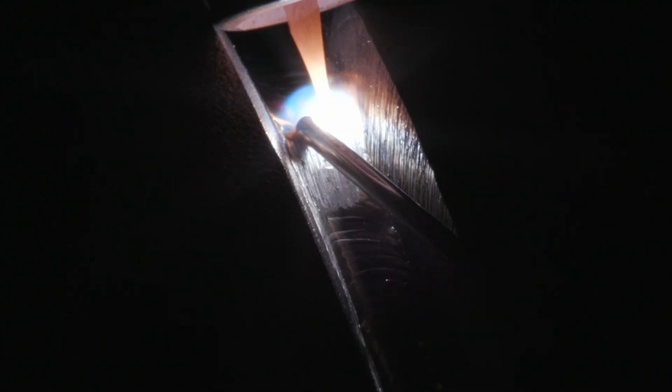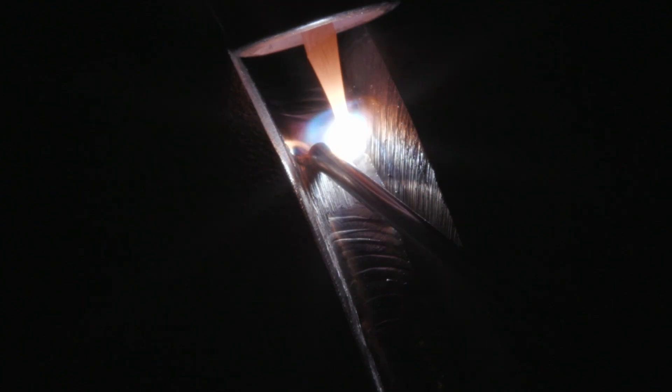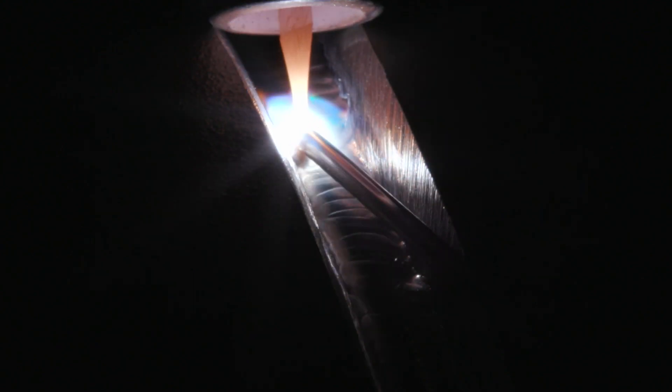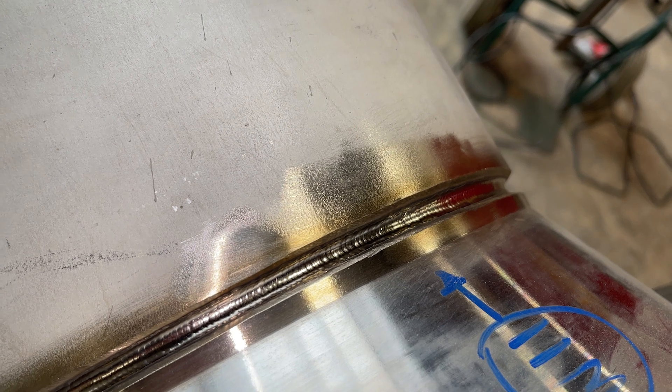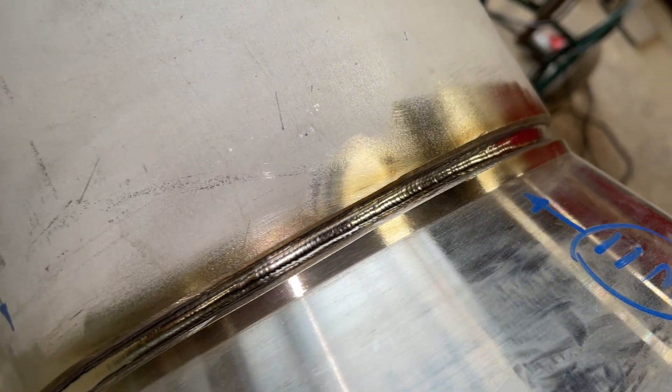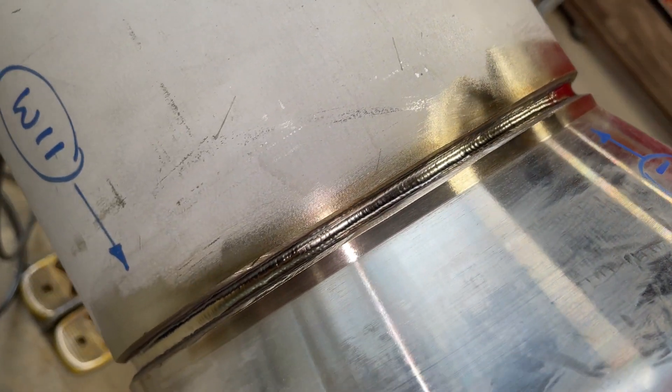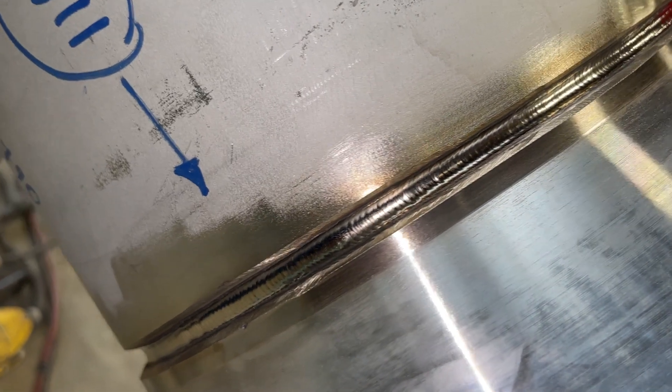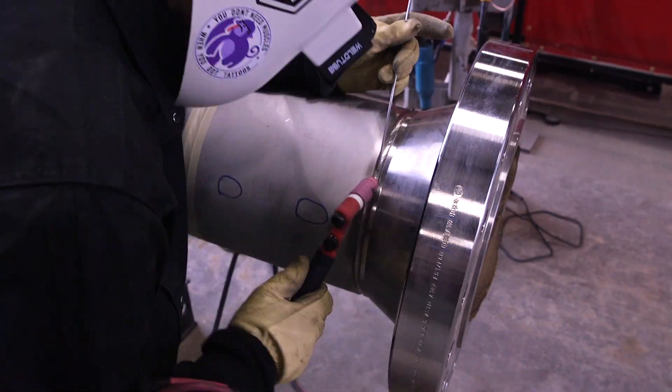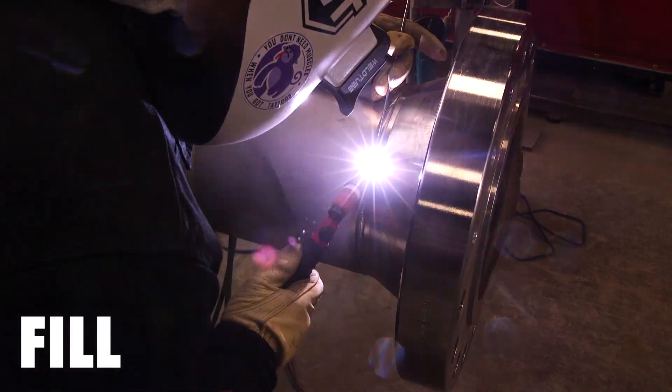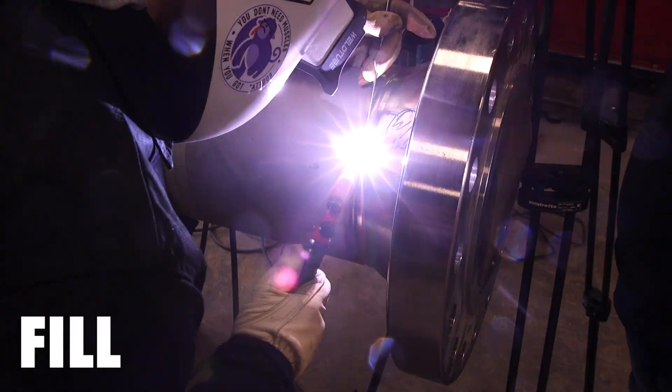So when I increase the size of pipe, I'll of course need more purge lines. Say a larger diameter will need like three purge lines, four purge lines, that kind of stuff. So the more purge lines you have, you could have a lower flow rate, and it'll have a very gentle argon flow, and it won't draw in, the atmosphere won't create turbulence, it'll inject with your weld puddles or welding, it'll be very gentle.